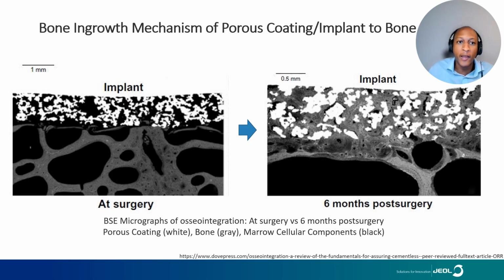And again, just to highlight the bone ingrowth mechanism between the porous coating and the implant. On the left side of the screen, in the image, we have the implant on the top, and on the bottom, we have the bone-facing surface. The porous coating is the white, the bone is the gray, and then the marrow cellular components are the black. At the surgery, in the beginning, you have the porous coating making contact with the bone, but you have no bone growth initially.